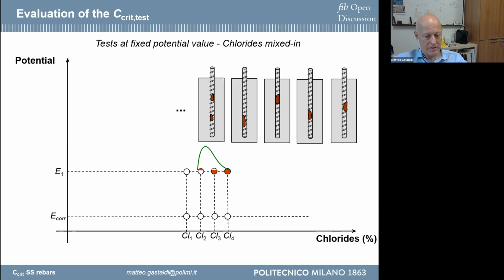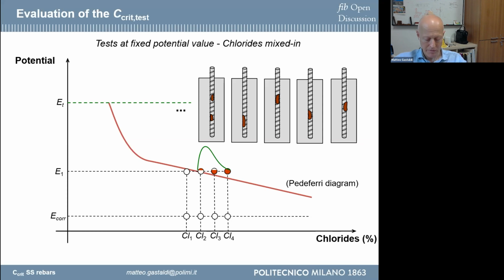If this test is repeated for different potentials, you can obtain the diagram also shown by Professor Andrade, the Pedeferri diagram, which gives the relation between potential and chloride content. You can draw the Pedeferri diagram considering the condition you take as the limit state for the critical chloride threshold, for example the lower value equal to 10% of samples affected by corrosion. So you can obtain the chloride threshold for the different potentials that you can have in the real structure, because you can use the potential of the real structure to get an idea of the critical chloride threshold in that condition.